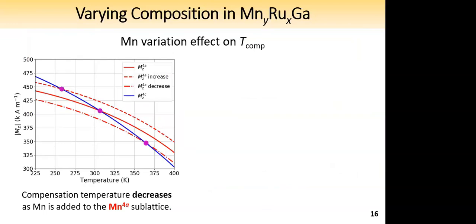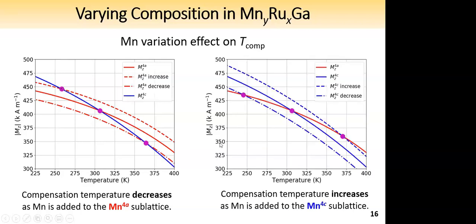So first, looking at the model, here I have the temperature dependence of the two sublattices. So we look at the solid lines first. This is the 4C sublattice in blue and the 4A sublattice in red. And so if we imagine the manganese 4A site is being manipulated, if I remove manganese from that lattice, then the magnetization will decrease. And that leads to an increase in compensation temperature. So you can see that there. Whereas if I was to increase the magnetization, that's like adding manganese onto the sublattice, that would lead to a decrease in compensation temperature. If we do the same exercise for the 4C sublattice, keeping manganese 4A constant, decreasing the moment on 4C would decrease T-comp, whereas increasing would increase T-comp.